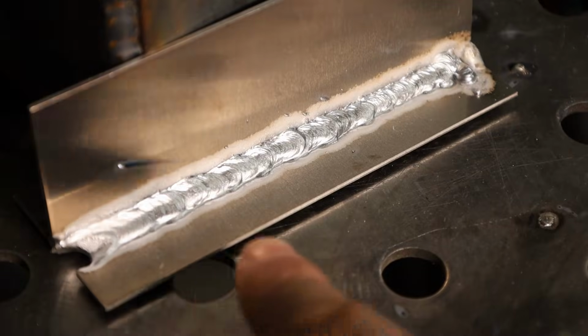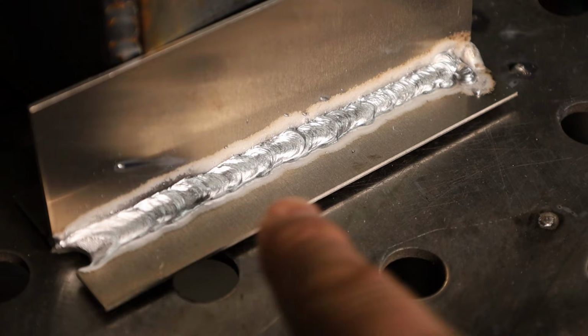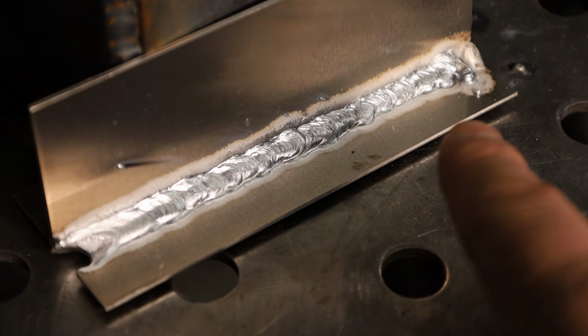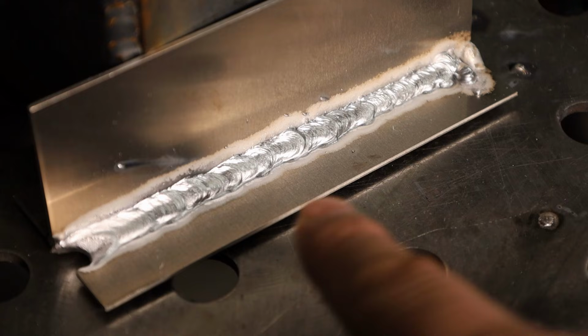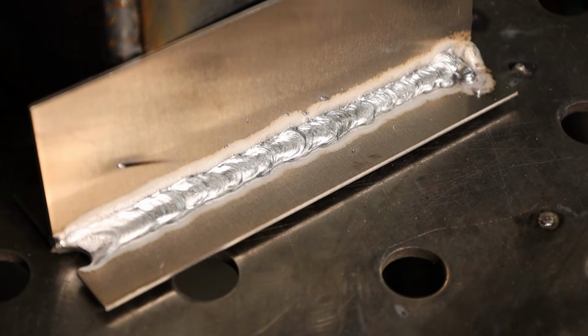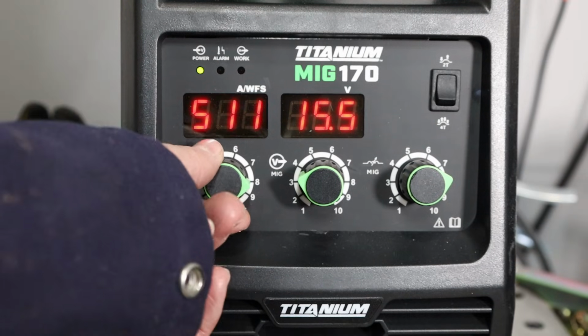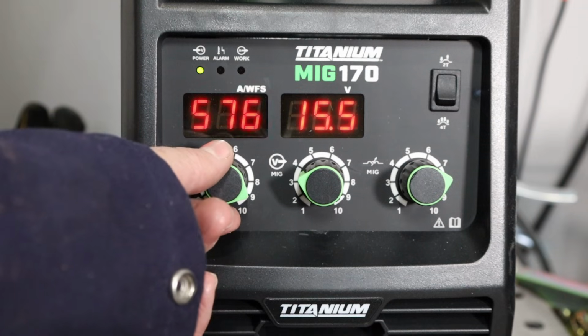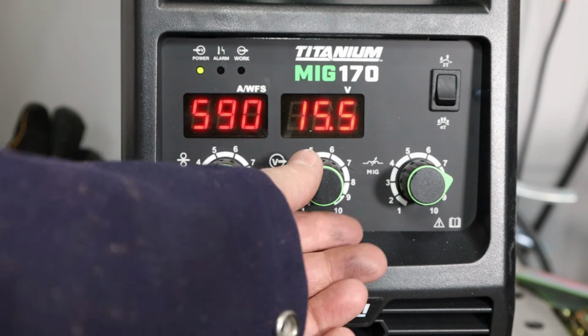But I'm still getting a reasonable result. I think if I put in smaller diameter, 0.03 inch wire, I could get the result that I want with spray transfer on this thinner material. But it's nothing reflecting poorly on the mechanics of the spool gun. It's just the system isn't able to handle it with that large a wire. And honestly, it's too big a wire to run this thin material on aluminum anyway. But I got a pretty reasonable result anyway, and I think a little more knob turning could get a little better with this, and that smaller wire would help quite a bit. Either way, it's still not too bad a result.